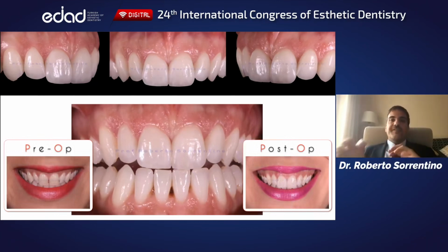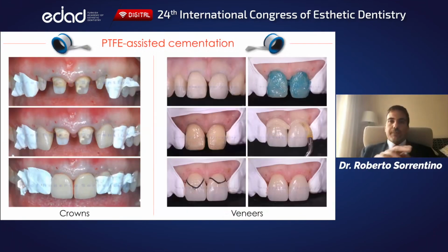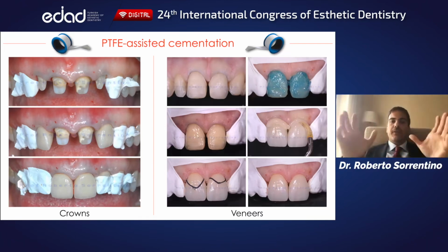Differently, if you decide not to use the full rubber dam, Teflon tapes can be useful to protect the surfaces adjacent to the cementation area, creating a kind of waterproof barrier. In my opinion, they can be used with simplified luting agents for the cementation of full coverage crowns with primary retention, and only as isolation aids in adhesive techniques involving non-retentive restorations requiring complete control of moisture and contaminants.